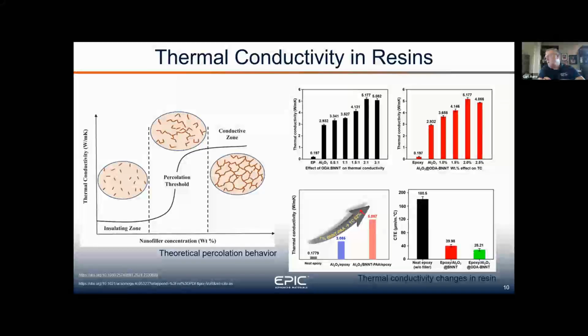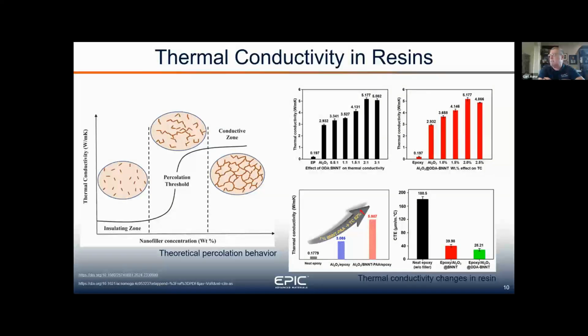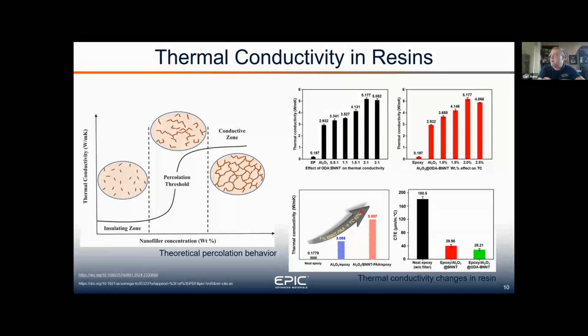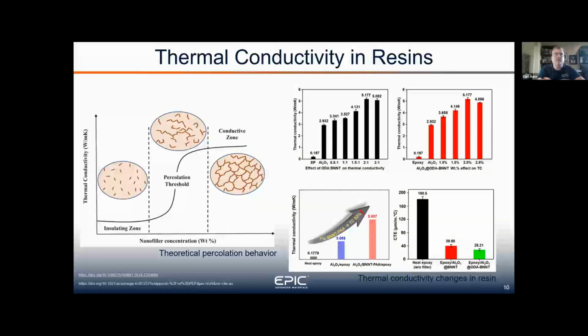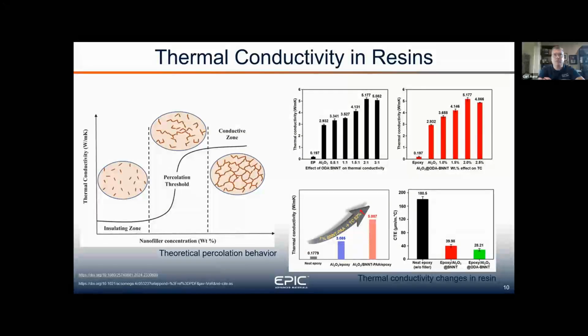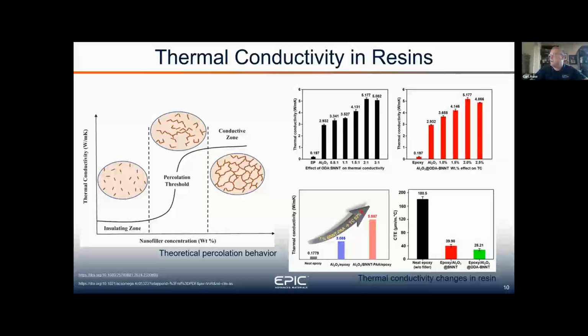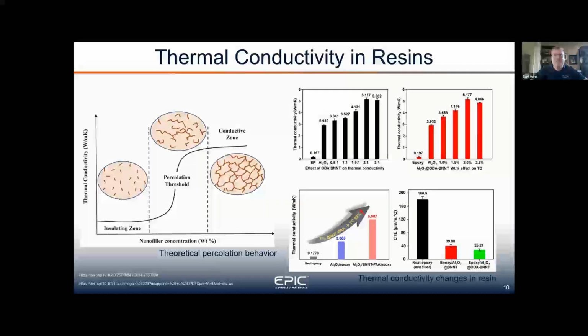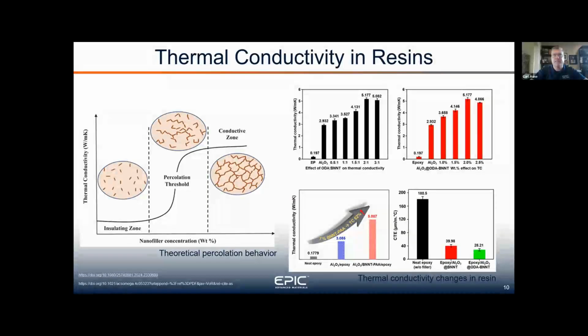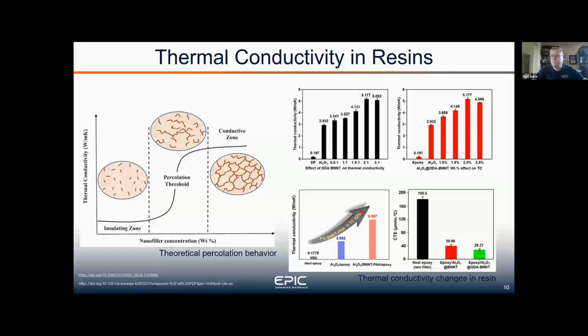I want to point out the chart on the top right-hand side, which shows BNNTs at 1.5, 2, and 2.5%. Notice that as you start adding the BNNTs into the matrix material, you start getting higher and higher thermal conductivity. But there becomes a point of too much is not a good thing. So when you get to about 2.5% in this specific matrix, you start losing some of the thermal conductivity from the scattering of the heat through the matrix rather than the transferring of the heat through the matrix.